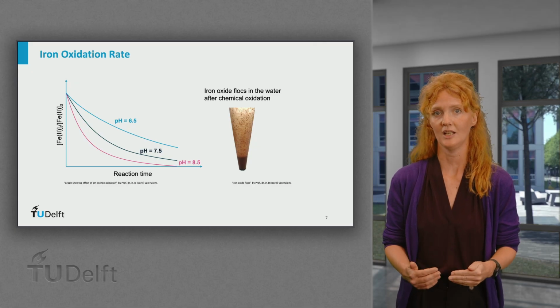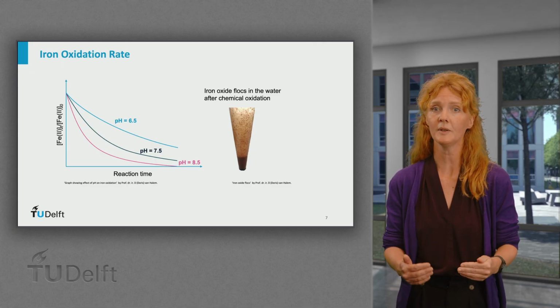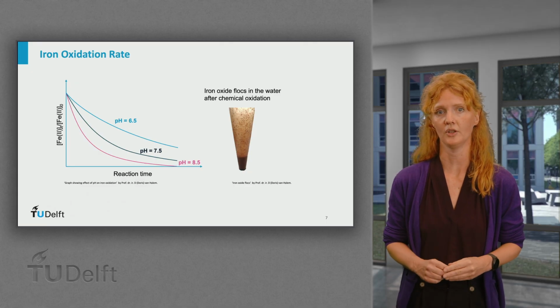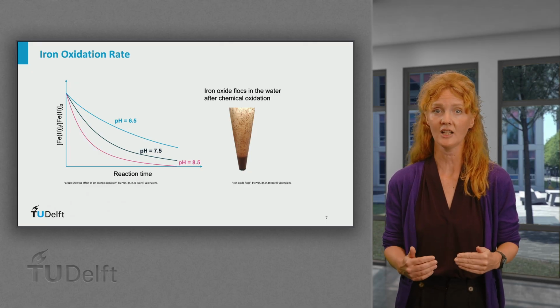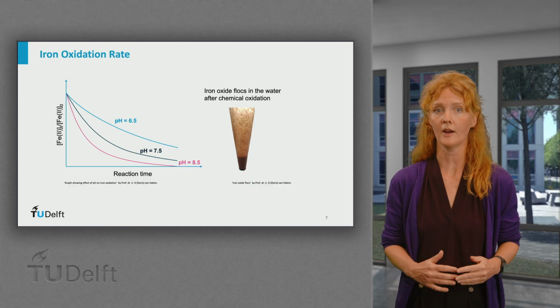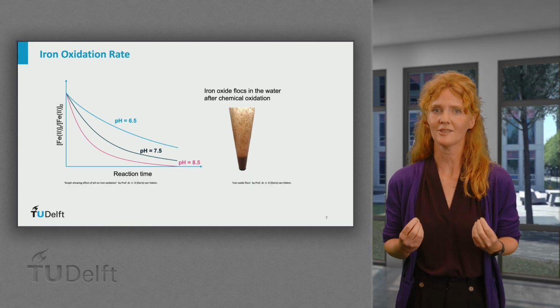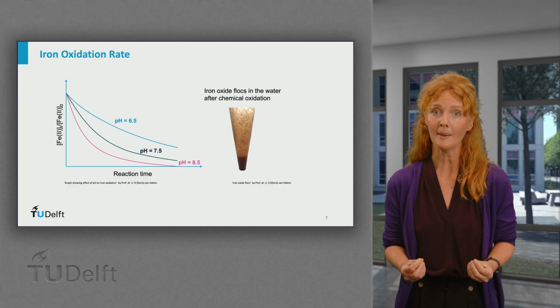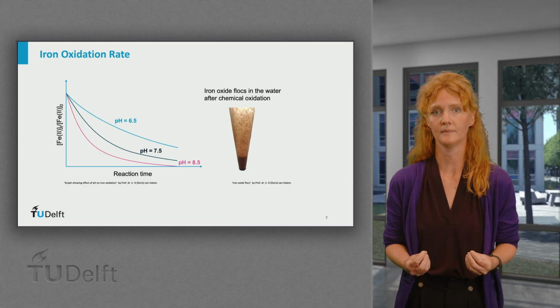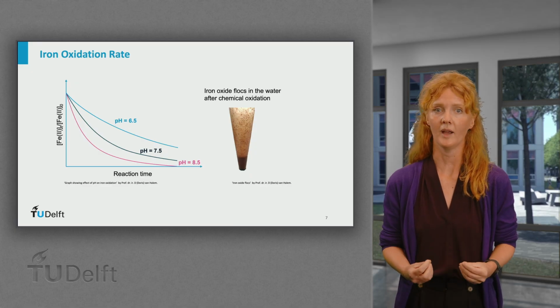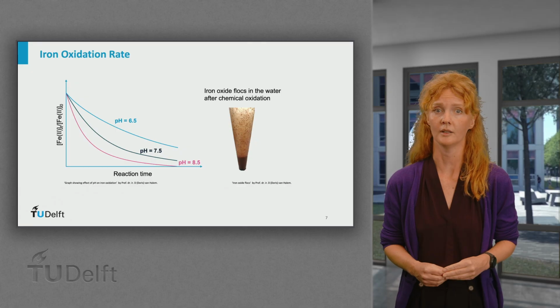Therefore, iron oxidation will immediately onset in the supernatant water prior to filtration. The chemical reaction will result in the formation of ferric iron oxides, which are solid particles that will be trapped in the sand pores of the filter. Well, this is a traditional way of removing iron from groundwater.